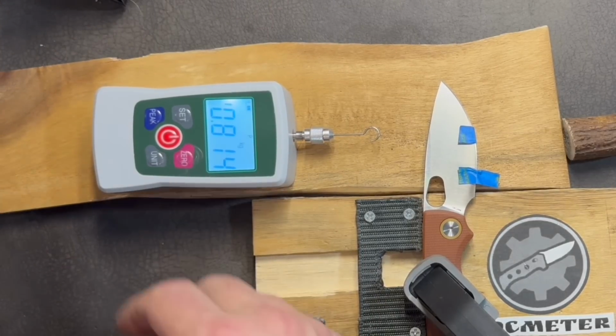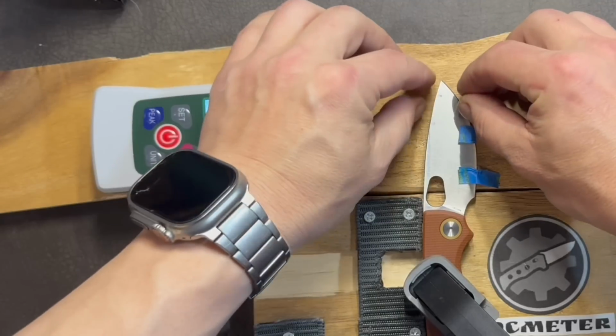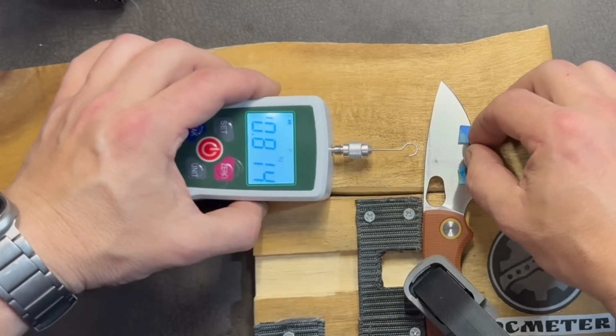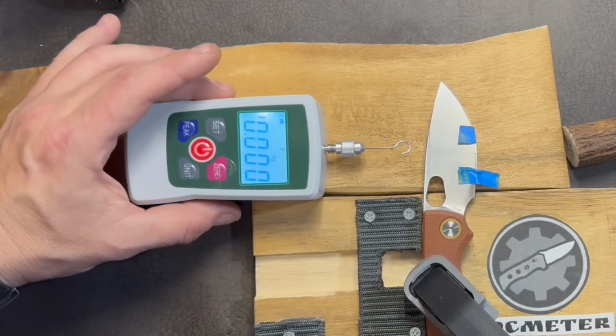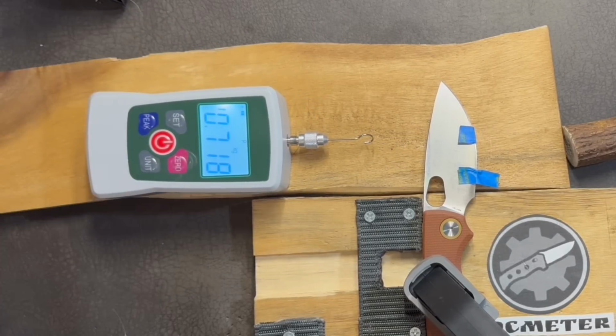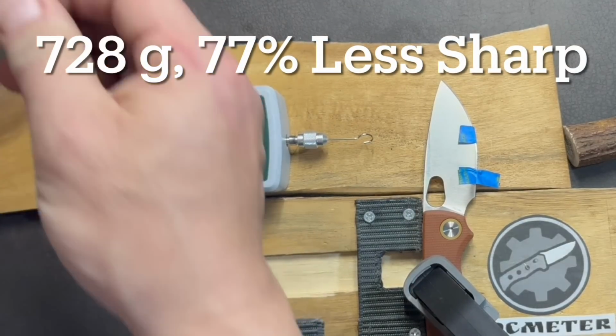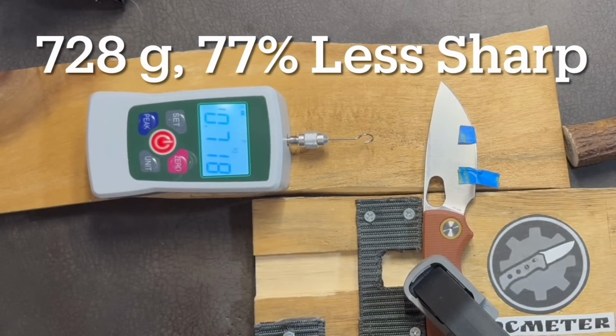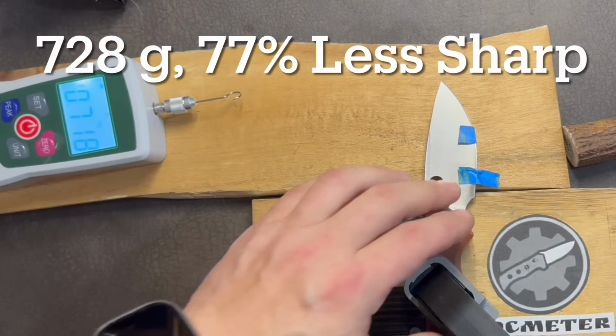14C28N Sandvik can be taken all the way to 62 HRC, but something already tells me this is not the case here, and Vosteed erred on the side of caution, basically selecting toughness over the edge retention. Don't worry, I will test the hardness next. For now, here's the average. 728 grams or 77% edge sharpness reduction after 40 cuts on a staghorn.